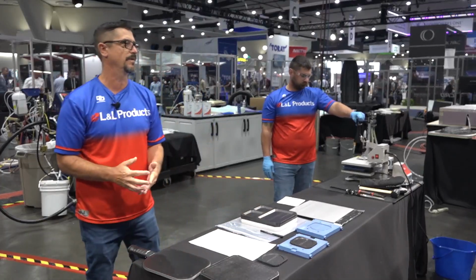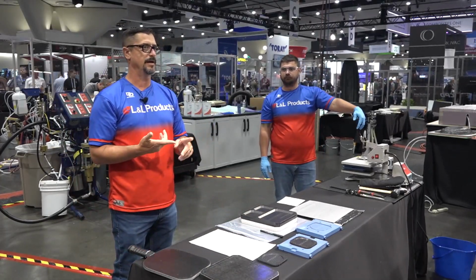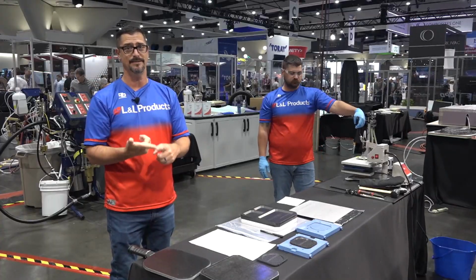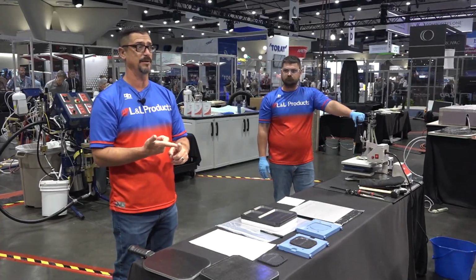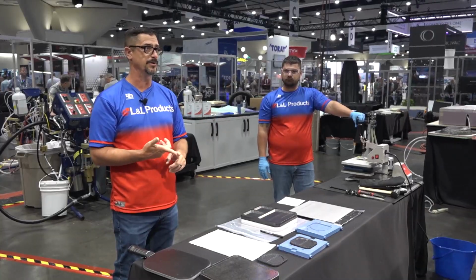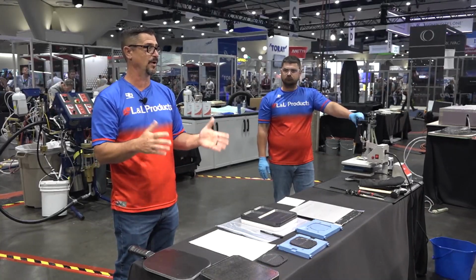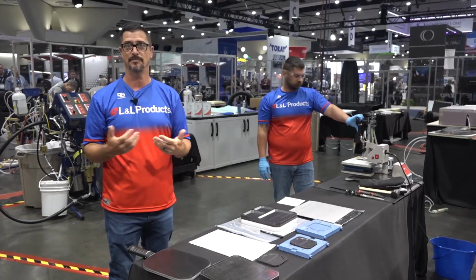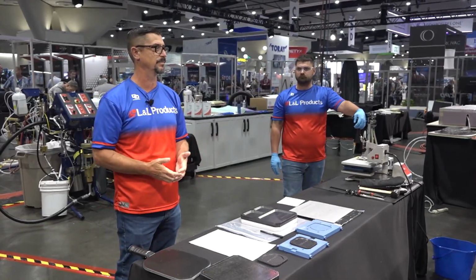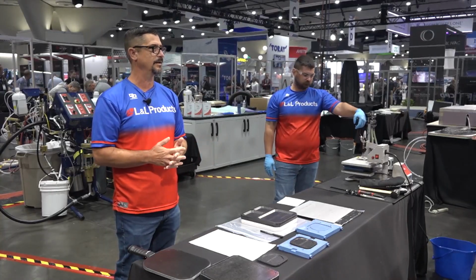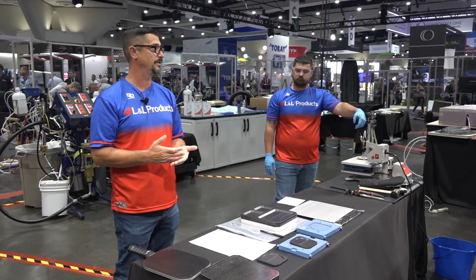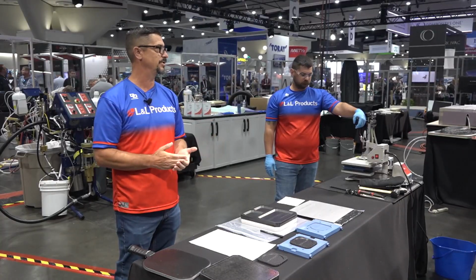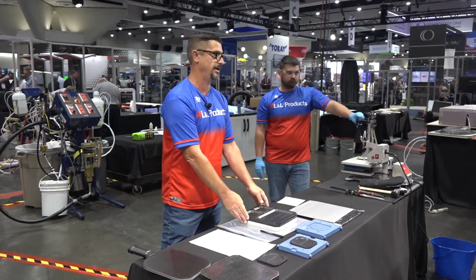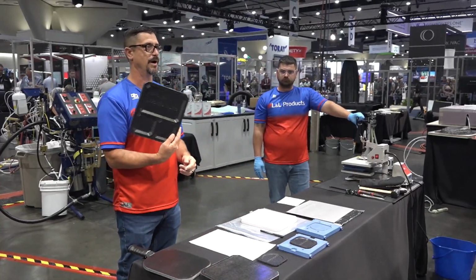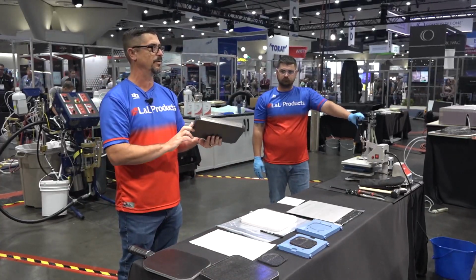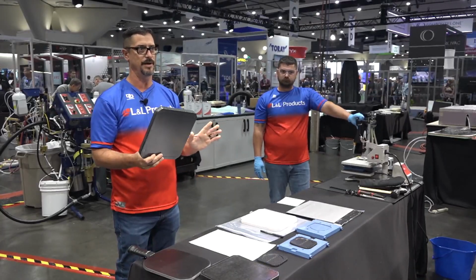So we mentioned the conventional method of machining. You think about that, you have a very expensive piece of equipment like a CNC mill that's tied up, that could be doing other things. You have the material waste that's generated because you're purchasing a foam and then machining it away, and you have to do something with the dust, either landfill it or reuse it somehow. But you're cutting out that step. You're reducing your overall cycle time because you're not doing that pre-machining process. You also don't have to do post-machining. The net shape part comes out. You may have a little bit of flash from the resin in the pre-preg to trim, but that's it.